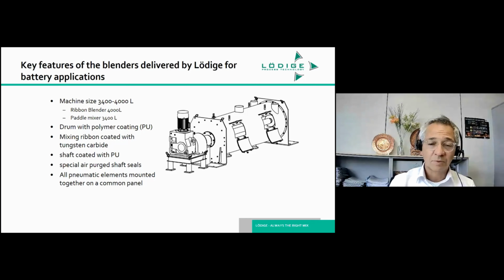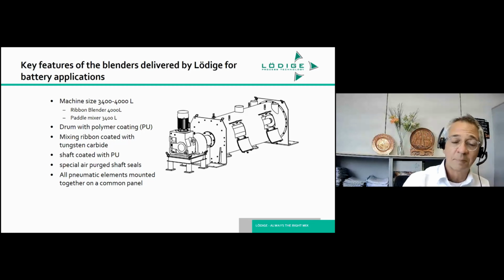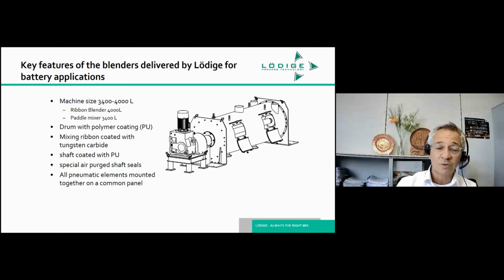The emphasis on preventing contamination, again, shows that we have to use some form of coating of all the product contact parts. In this case, we could use a polymer coating because the mixing action is not so intensive. Hence, polymer coating, in this case polyurethane, was deemed appropriate for the task. For the mixing tools, we opted for tungsten carbide still, because the intensity was still so much that polyurethane was not deemed to be that good. The shaft was coated again with polyurethane, air purge seals for keeping the toxic material inside, and again, all pneumatic elements positioned on a panel.